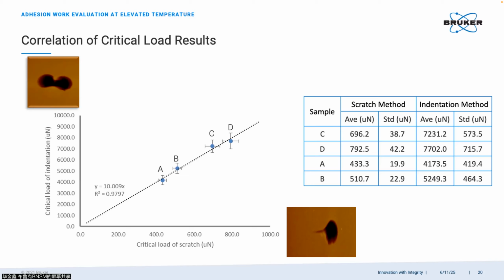That means if you have a data set of your interfacial bonding monitoring using scratch test, for example, and one day you would like to apply indentation test, then you don't have to give up all the big data from before, because you can have a proportional testing like this. You can select a strong interface and a weak interface, and then perform indentation test together with scratch test. Then you will find the proportion, and then you can convert all the big data of scratch test into indentation test.